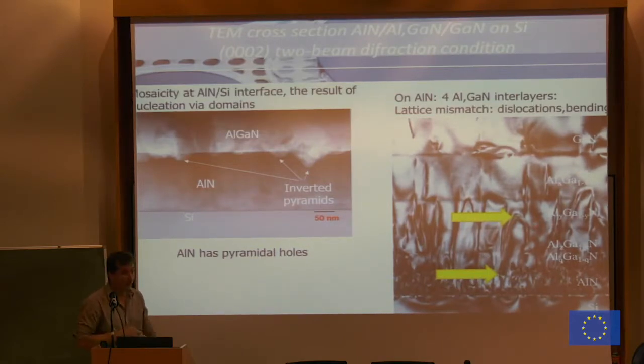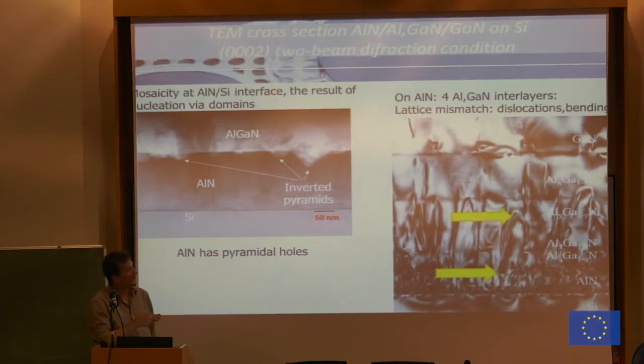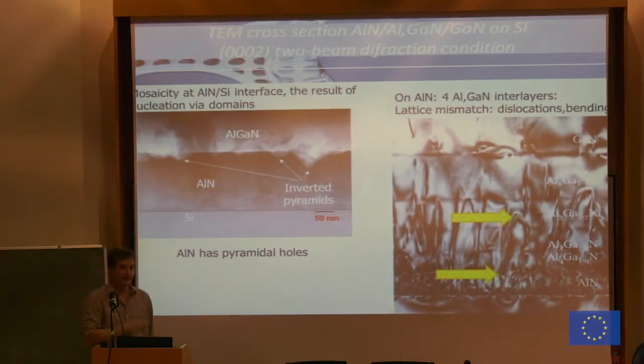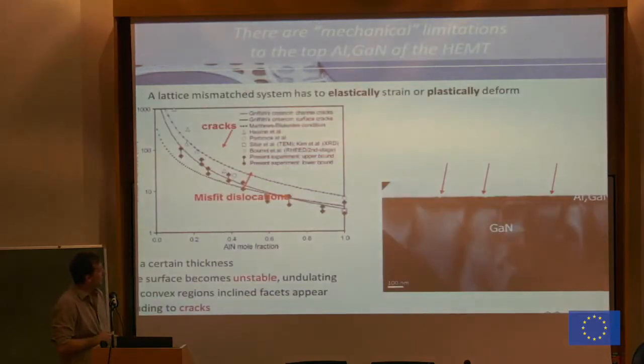So it is also a way to improve the crystal quality as you go up, which is the case in gallium nitride. If you grow gallium nitride on silicon, the starting layer here has a typical dislocation density of 10 to the 11th dislocations per square centimeter. And by this mechanism, by having them annihilate as you go up, typically the gallium nitride stack on top already has a factor of 100 fewer dislocations than it has at the bottom.